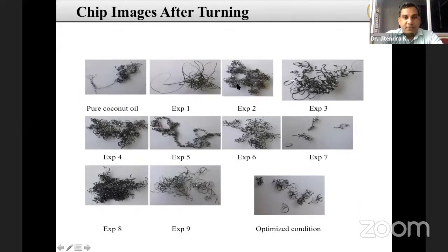In the chip morphology also we observed that the more curly chip is found in experiment 3. You can see that particular plain chip, and it is thicker than the others and also more curly, so that's why the forces are very high in experiment 3, and it also gives the higher surface roughness. In experiment 7 we get a discontinuous type of chip.